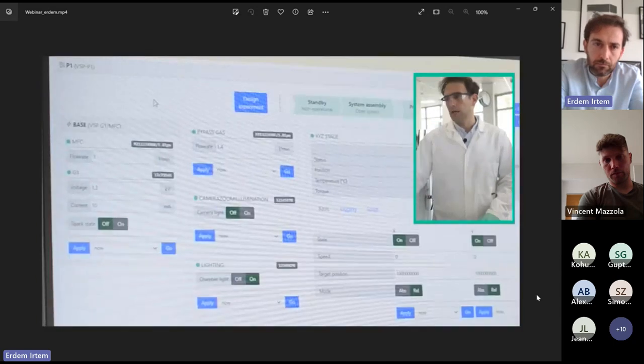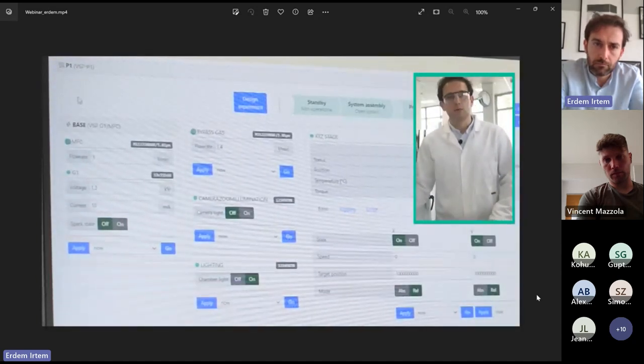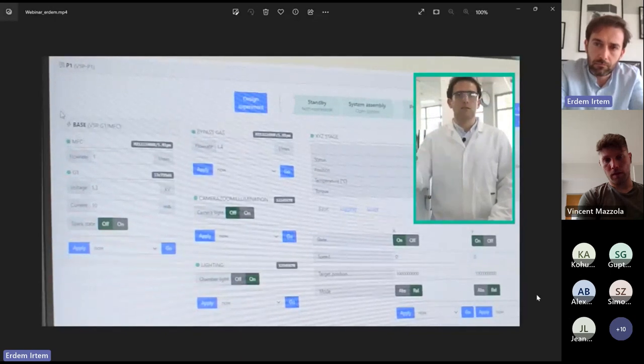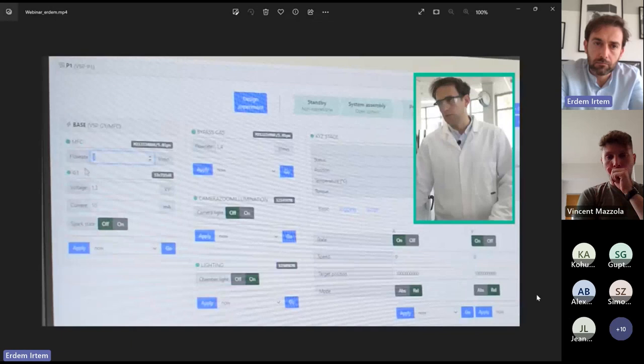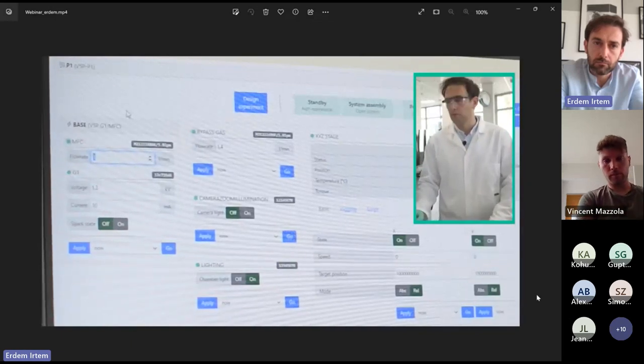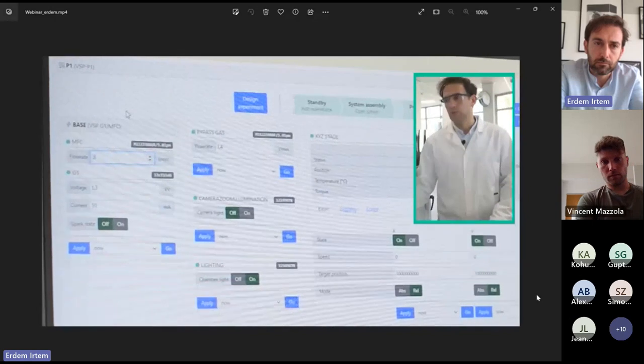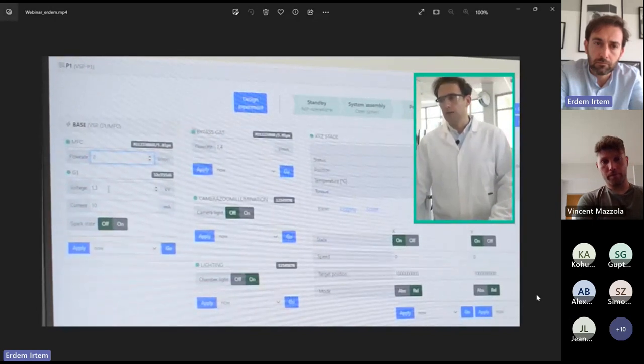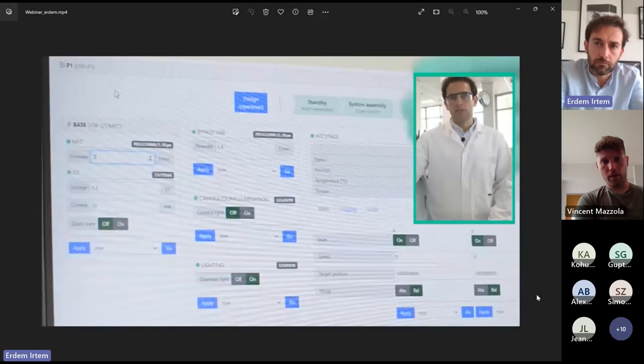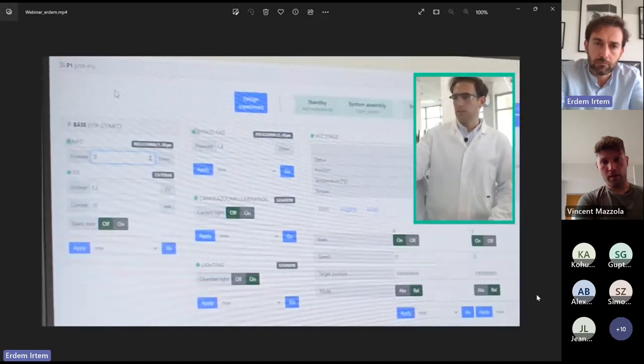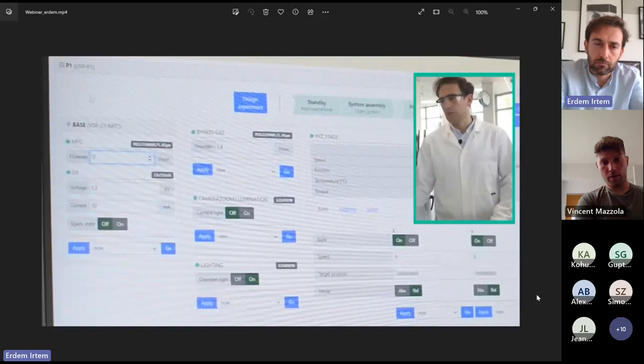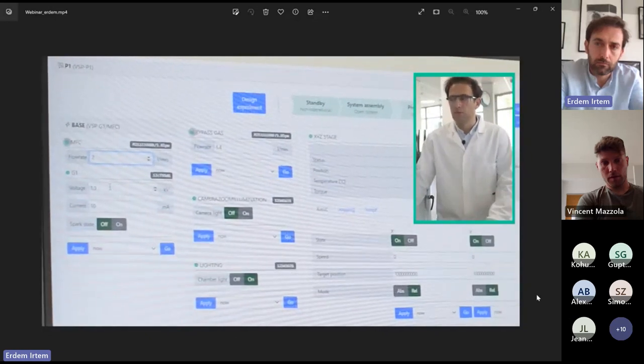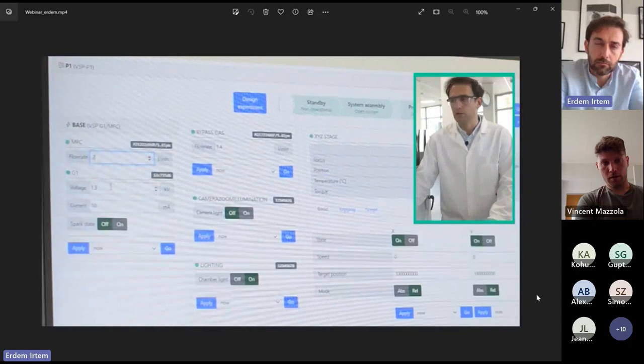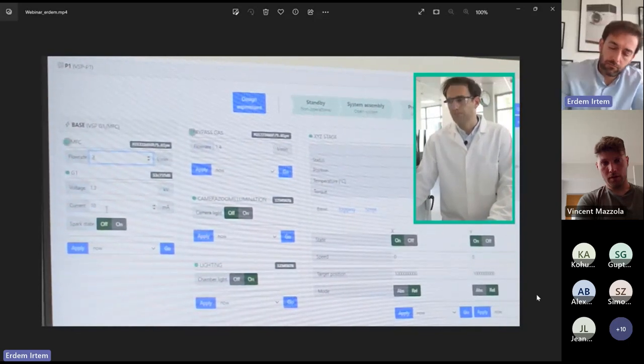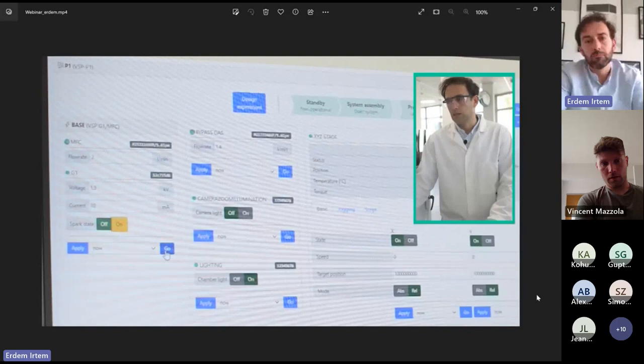On the left side, you will have the main gas flow that feeds the nanoparticles as a stream of aerosol. So you can put here a flow rate of 1, 2, 3, 4 liters per minute. So right now we are going to put 2 liters per minute. And then also you have, in the same unit, the voltage and current applied to generate the spark. In this parameter we are going to ablate iridium, and we are going to apply 1.3 kilovolts and 10 milliamps. So we can start the spark state on and click go.